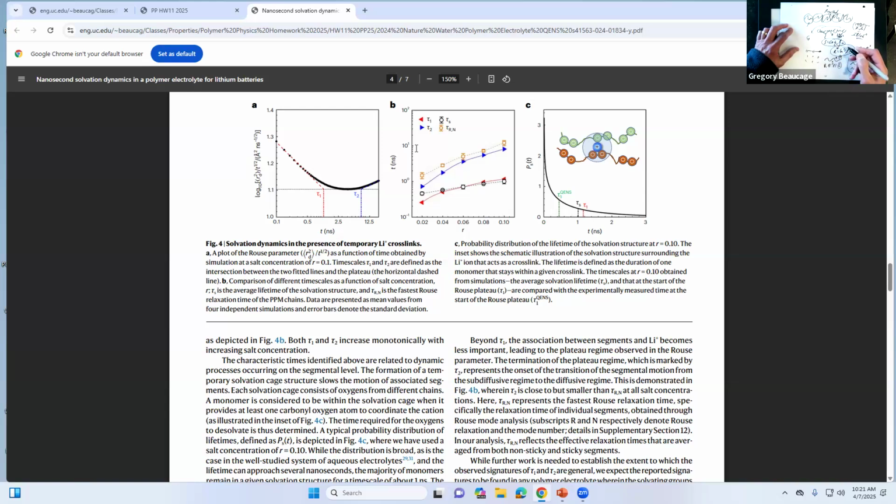So the N is the Rouse number that he arbitrarily picks, some number that's smaller than the whole chain but bigger than a mer unit, so that Gaussian statistics applies to it. Then you do a force balance on that. The force is the velocity times the friction factor, plus the spring constant times the distance that the spring moves.